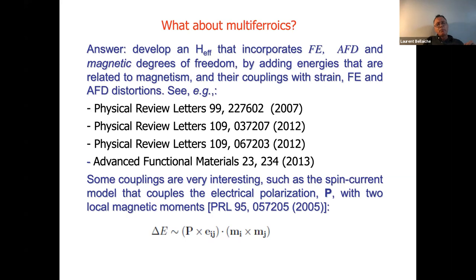This is known as the spin current model. What is interesting is that on the left side, you have P cross e_ij, where P is the polarization, the electrical one, and e_ij is a unit vector along a special direction. For example, in bismuth ferrite, it would be along the 1-1-0 direction. On the right side, you have a cross product between M_i and M_j. So you have polarization via P cross e_ij, and the magnetic one, because of M_i cross M_j.